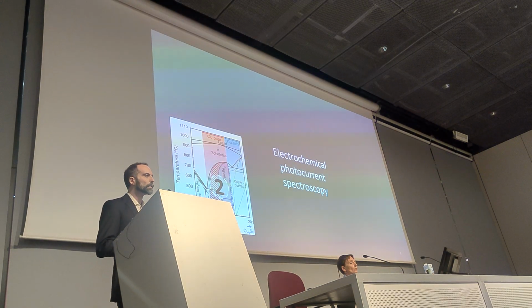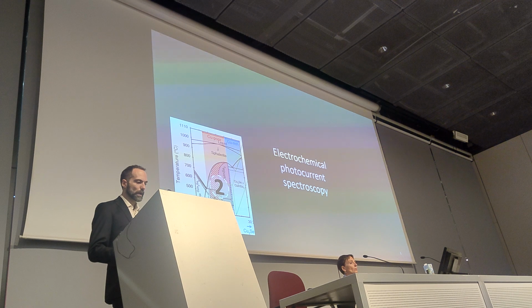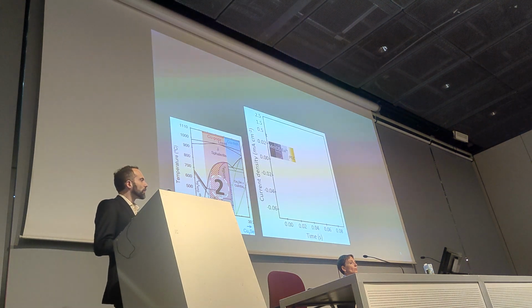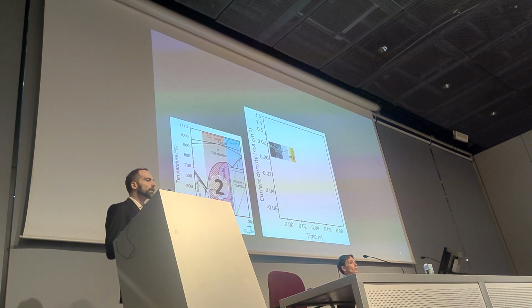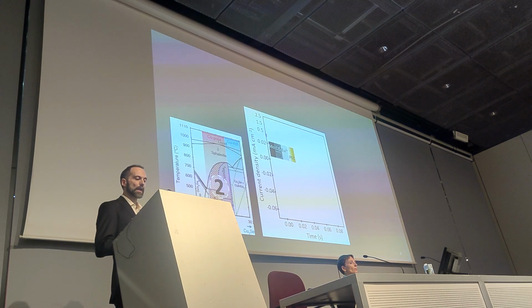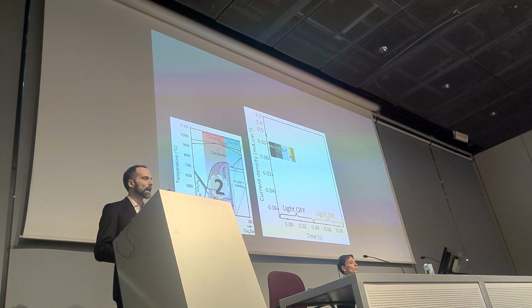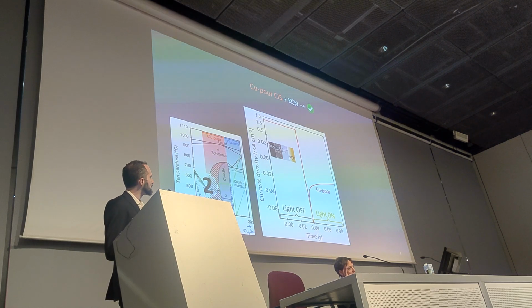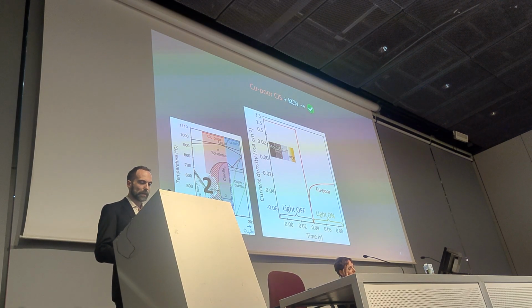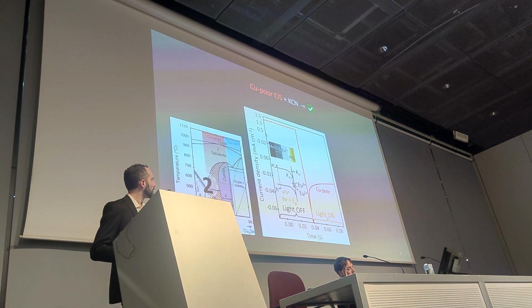We looked into electrochemical photocurrent spectroscopy as a technique to try to understand what is going on. In this technique, we immerse the absorber into an electrolyte solution containing a redox couple, and we then record the current flowing through the system, at a fixed potential, when we turn the light on. As we move to the copper poor conditions, we get a transient such as this with a spike. Now I'm not going to talk about the spike. This is something that was known for long in the literature, but what we see here effectively is a photocurrent that is due to a collection of photogenerated electrons by the europium 2+ redox couple in the solution.